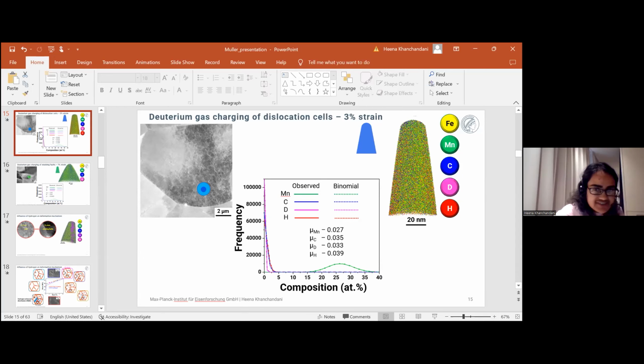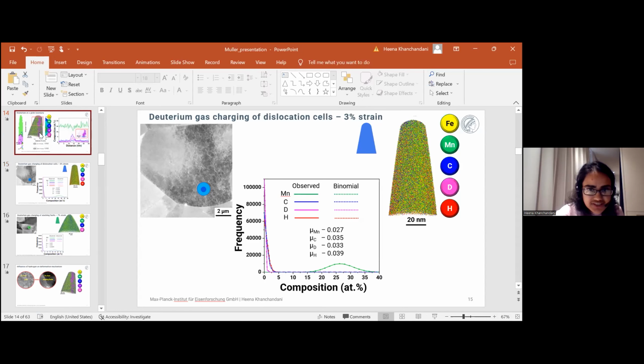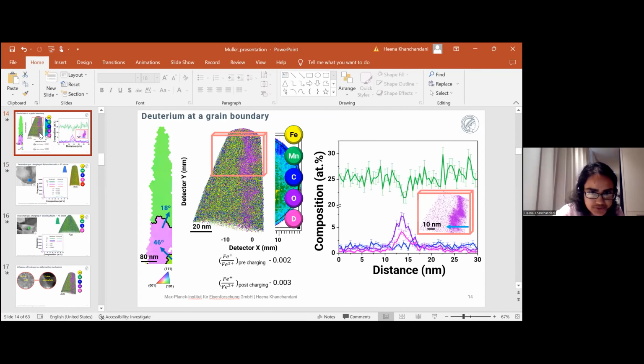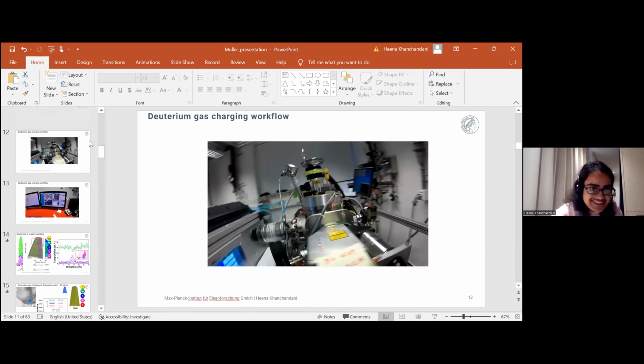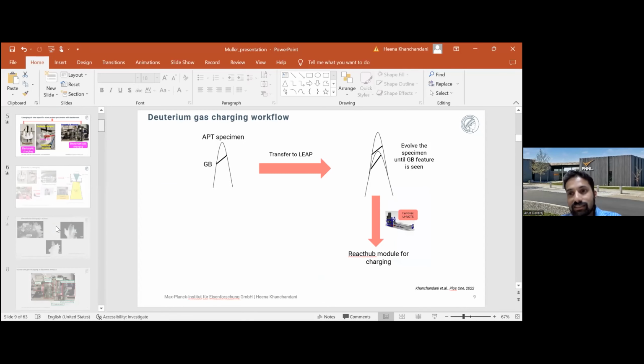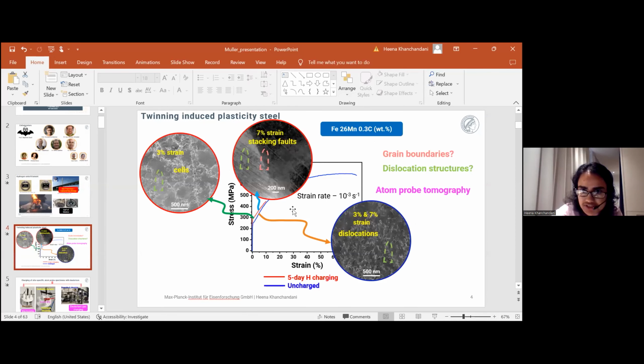not getting segregation at dislocations has actually several reasons. One here is the strain rate that I used in my tensile tests. That was 10 to the power minus 3 of the strain rate, which is a little bit higher. So maybe when we are deforming the samples, hydrogen is not following the dislocation cloud, because the deformation is fast and the diffusivity of hydrogen in austenite is slow. So these hydrogen atoms are not able to follow the dislocation cloud. That is one reason. So that's why we do not see it.